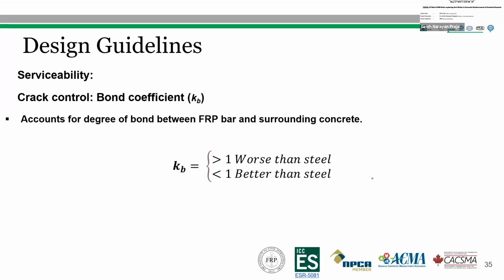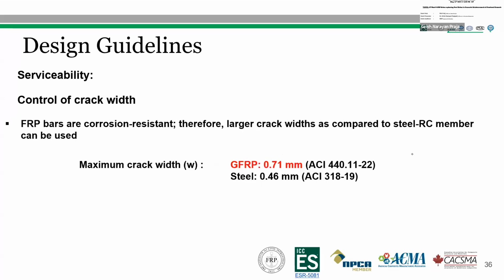So the bond coefficient accounts for the degree of bond between the FRP bar and the surrounding concrete in ACI and CSA design standards. If the bond coefficient is lesser than 1, it is found to be better than steel. The bond coefficient generally depends on the external surface of the FRP bar, and it generally varies between 0.7 to 1.2. According to ACI 440, it is taken as 1.2. Since FRP bars are corrosion resistant, wider crack widths as compared to steel reinforced concrete members can be tolerated. So according to ACI codes, the maximum crack width for GFRP bar is around 0.71 millimeter.